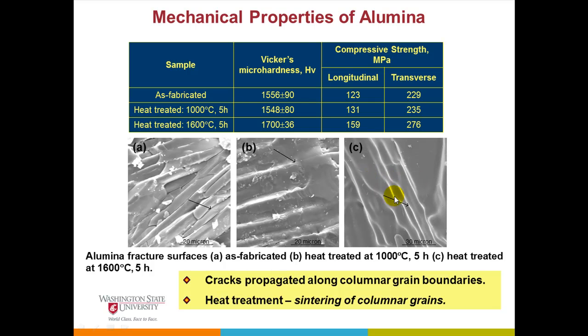By the time we are heat treating at 1600, there's a lot of sintering we believe is happening. As a result, all the clear grains you could see in the as-processed structure are gone, leaving a nice smooth fracture surface. So if we need to do ceramic processing like this, a post-processing heat treatment may be necessary for a composition you're interested in.